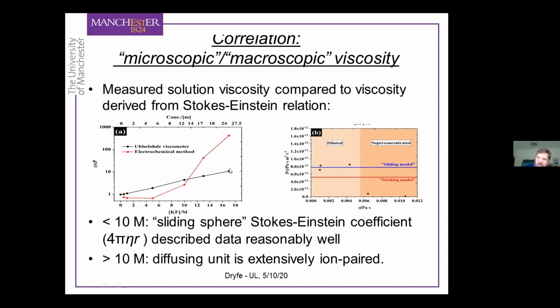But when you compare that macroscopic viscosity with the microscopic viscosity you extract from the electrochemical experiments, you can see that the apparent viscosity on a microscopic level doesn't change very much at the low electrolyte concentrations. But when you get to the high electrolyte concentrations, the viscosity changes massively. It goes up by not 1, but 2 or even 3 orders of magnitude for these highest electrolyte concentrations. So why is that? What's the difference between the viscosity on the macroscopic level of the solution as a fluid moving through the viscometer and the redox probe moving through this electrolyte solution? Why are you measuring two different things?